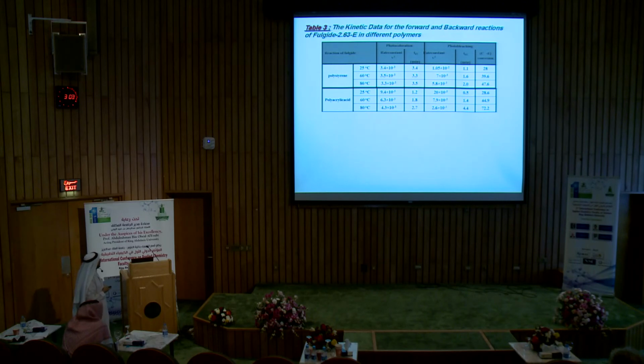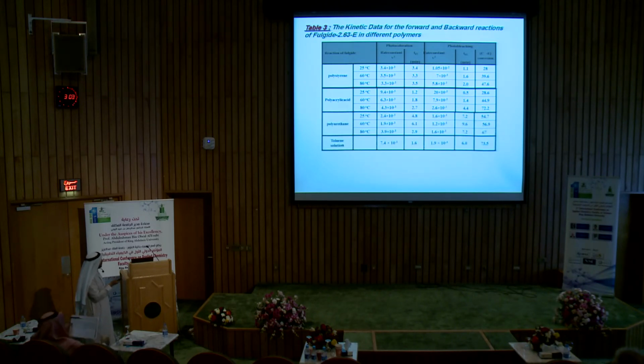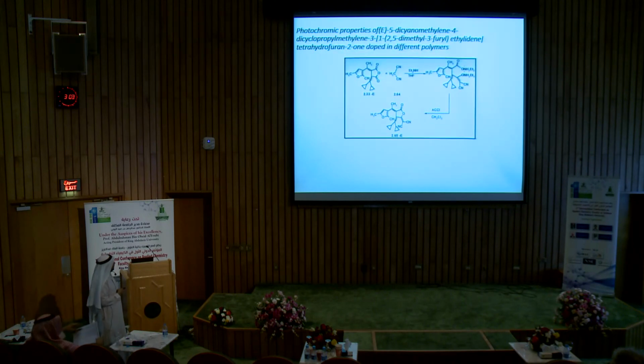This table shows the half-life and the rate constant for the coloration and discoloration of this fulgide in different polymeric materials, and also in toluene solution for comparison. In 1993, I think, when I was doing my PhD at Cardiff University, most of the people in the world were trying to shift the maximum absorption of the cyclized form of fulgide to beyond 600 nanometers. And one of the attempts we made at that time was to condense the fulgide with malononitrile in the presence of a moderate base, then cyclize again.